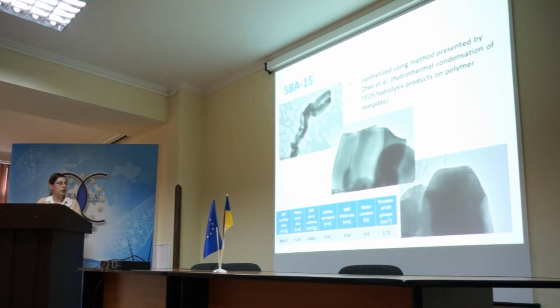They are shaped as rod-like particles, and they are very long, and they have about 500 nanometers in diameter. The mean pore size in this material is about 6 nanometers. So nimodipine can be loaded inside the pores. Here the drug loading procedure is presented, but I'm not going to describe it in detail.